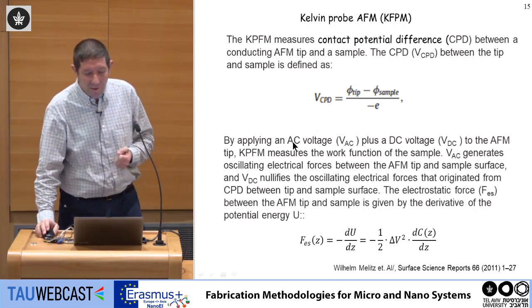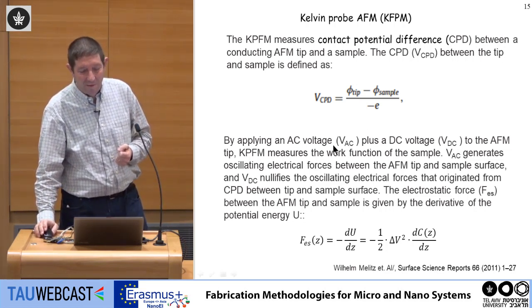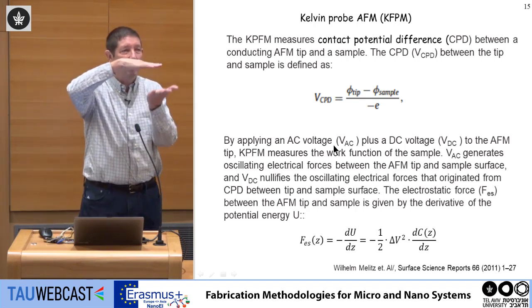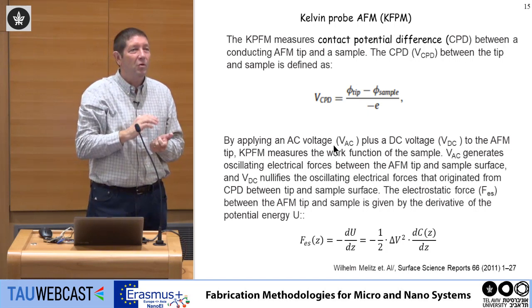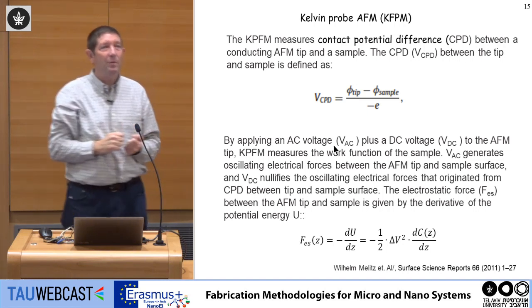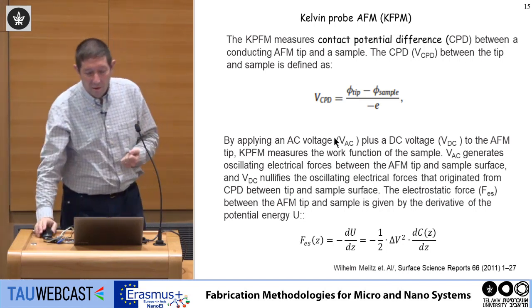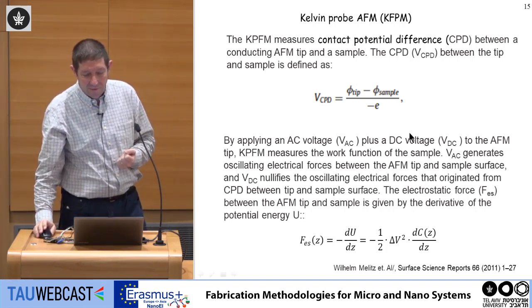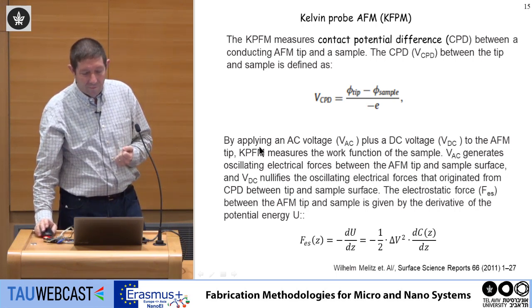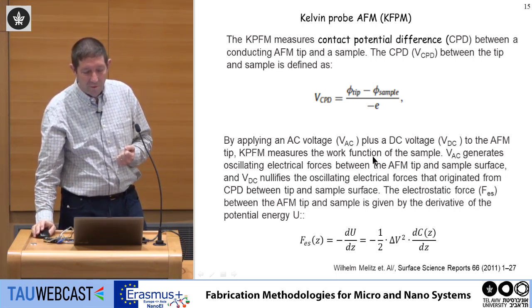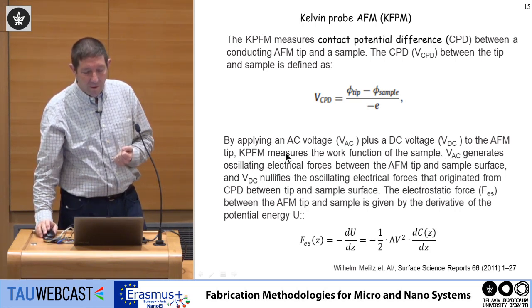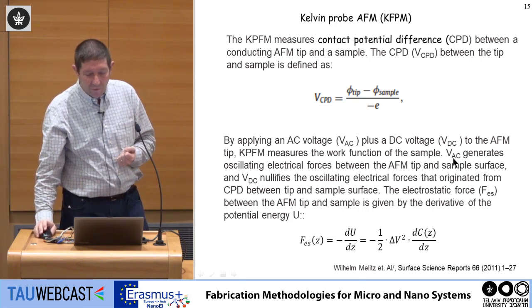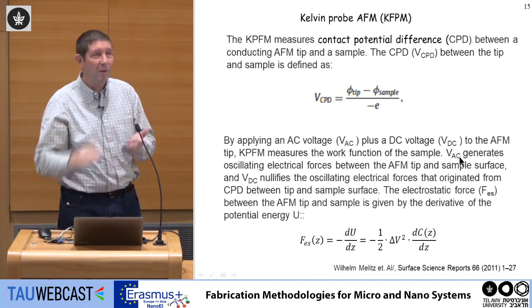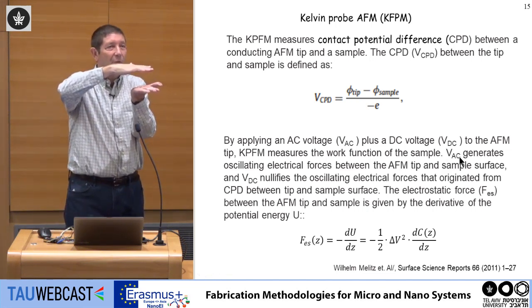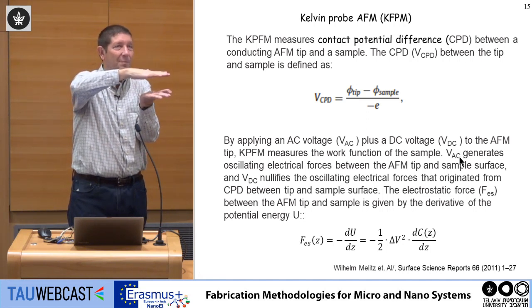What is possible in this method is that we apply an AC voltage. It's not only that we are vibrating the tip or applying force on the tip, we also apply voltage to the tip. In the Kelvin probe we can oscillate this signal, and we apply an AC signal and a DC signal. Using this technique, you can measure the work function of the sample. Now, because we apply an AC voltage, we are generating a force, because this is like a capacitor with a spring.